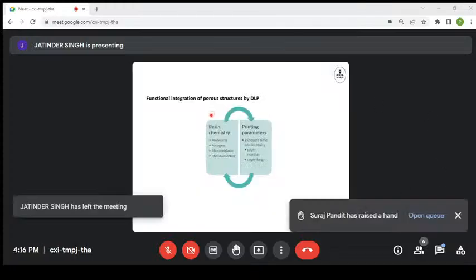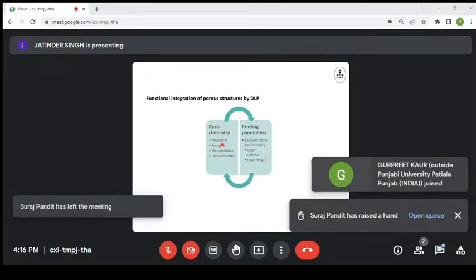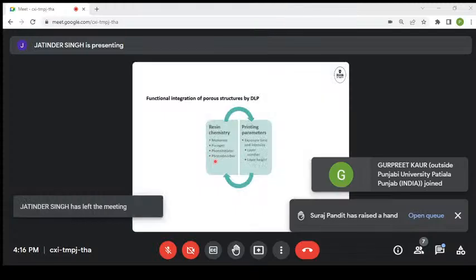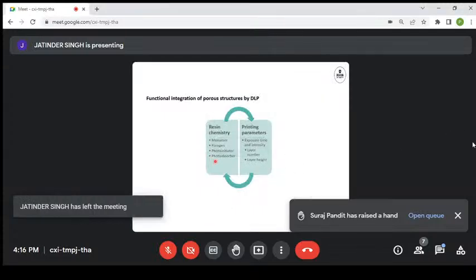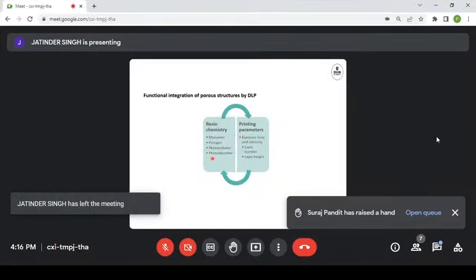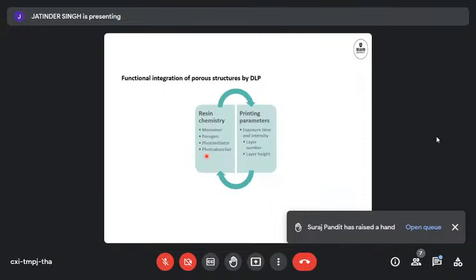So, functional integration of porous structures by digital light projection printing. The handles that we have to manipulate are the resin chemistry, the monomer itself, which determines hydrophilicity and hydrophobicity, the porogen that you can add to add porous properties, the photoinitiator and the photoabsorber that you can use to play with the polymerization kinetics, and in that way, manipulate the pore size to tune it to your application.